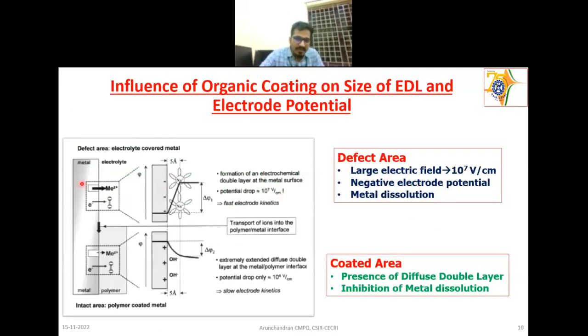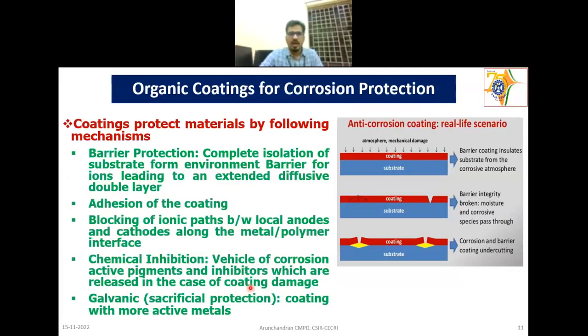So here metal dissolution will happen. At the same time, when you have a coating, the presence of a further diffuse double layer due to the coated area leads to inhibition of metal dissolution because of slow electrode kinetics. So now we go to how a coating protects a substrate from corrosion.